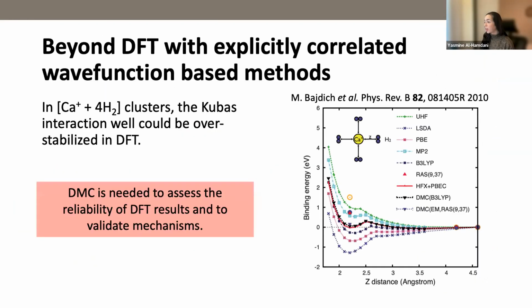No, yeah, indeed. So yes, we did manage to use PBE actually. I was hoping to actually use PBE plus U, but the way that PBE plus U is implemented in Quantum Espresso made it very difficult, because calcium is not a typical element that you would apply the plus U to. So in the end, we just did the test with the PBE orbital instead. And the results were basically in agreement for the QMC side. So using PBE or LDA orbitals led to the same adsorption energies, I think within 2 sigma.